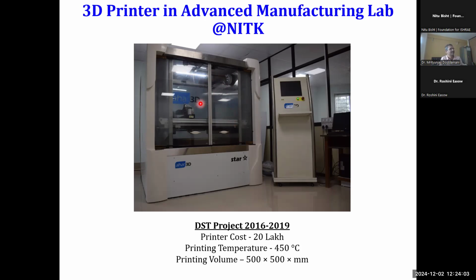So here the filament is being fed. And all these filaments, we never bought from the market. We bought the raw material and extruded the filament, and that's how the DST project funded one equipment known as a twin screw extruder. And through that filament, we printed on these 3D printers. It's a completely open source system. And you can see the printing temperature here. It is up to 450 degrees C. Generally, 3D printers are available from 15,000 onwards, but they have a limitation on build volume, material usability, and typically the printing temperature, which is up to 250 degrees C, sometimes 280 degrees C.